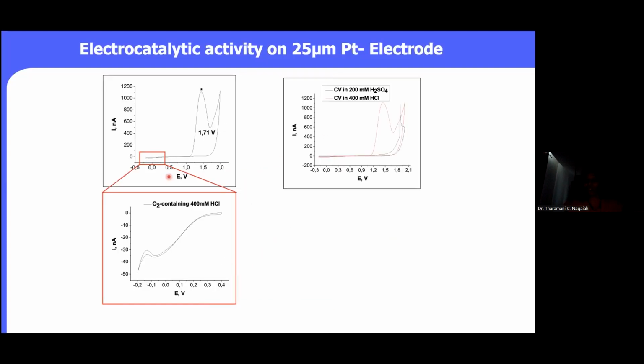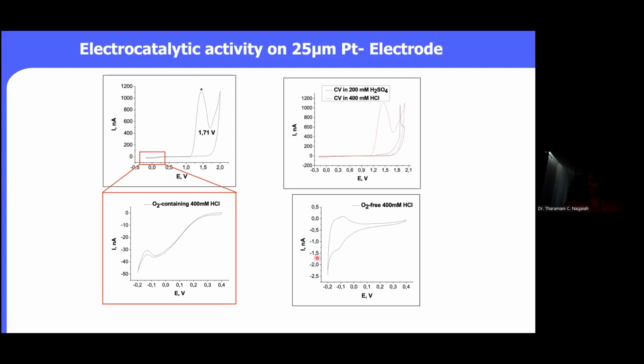To confirm whether the peak is due to the chlorine oxidation or not, we have done a control experiment in the absence of chloride ions. You can see that the oxidation current is increasing at 1.8. That means this peak is due to the presence of the chloride ion. And again, we can see that this is the typical behavior of the hydrogen adsorption and desorption peak, especially in acidic media.